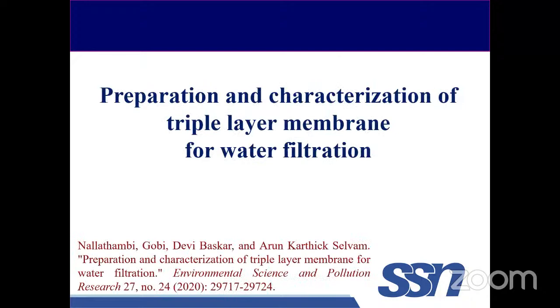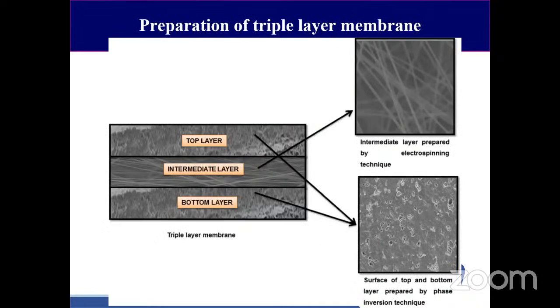On the next, the other drawback that we found in the past study is these nanofibers are quite fragile in nature. So the handleability is quite a difficult task. So what I mean is mechanical strength. In order to improve the mechanical strength as well as the functional aspects of the membrane, we further did research on preparing a triple layer membrane, where we utilized 3 layers, right?